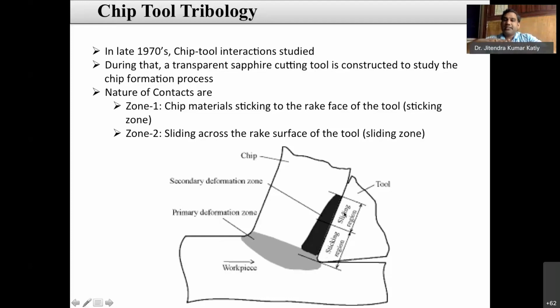When you stick, there is no material eliminated from the surface. But when it tries to slide after sticking, then the material is eliminated. So that is the basic reason for the two zones observed in chip tool interaction. Further, we observed the chip tool interaction with an IR camera and an optical profilometer. You can see a sticking zone and then a sliding zone a little away. The temperature at the sticking zone is higher, which is why you can see that very high temperature regime there rather than in the sliding regime.